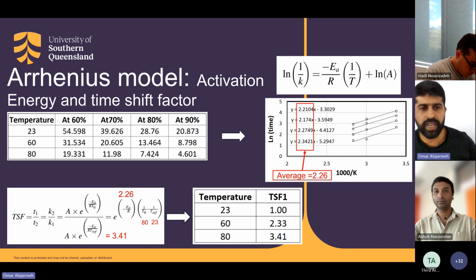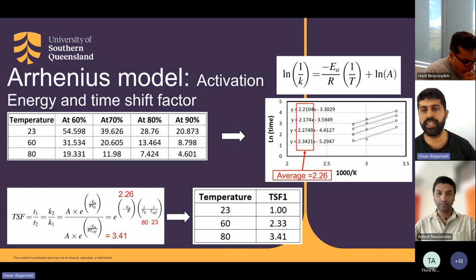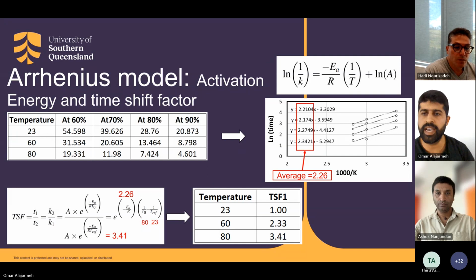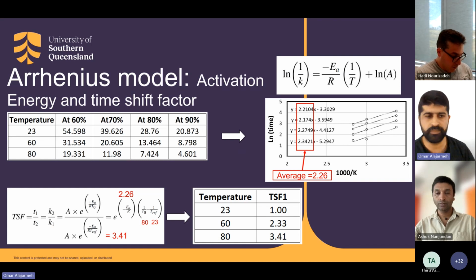The outcome of that was plotted in X and Y according to the equation that we saw two slides ago, which is the linear equation. The linear equation expresses activation energy as the slope of the linear line. So from plotting these relationships, we found that the activation energy is the slope of those numbers, and we got that averaged at 2.26. Different material, different average, different material, different activation energy.